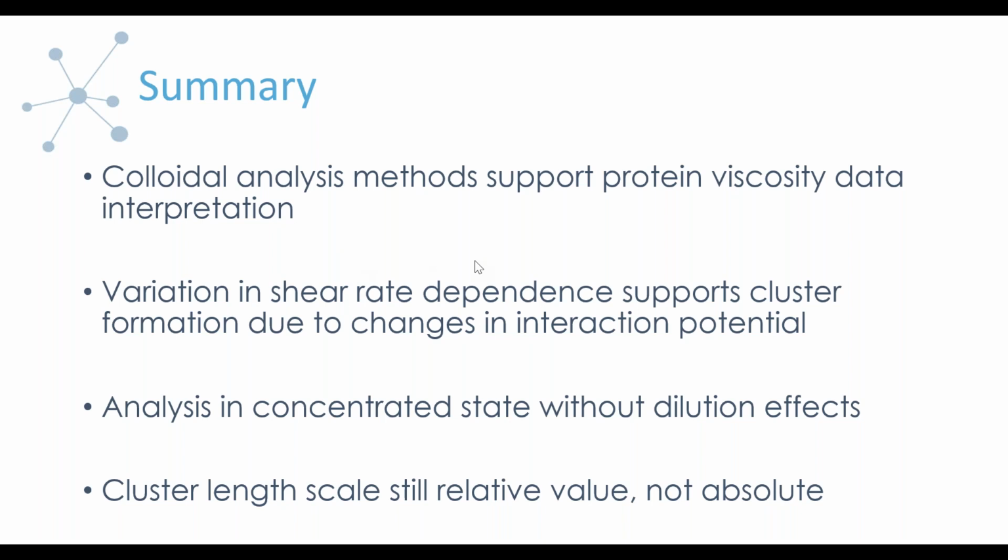Someone asked a question also about what viscosity at very high shear rate means for the colloidal framework. I didn't talk about that too much because we don't have that data, but that high shear plateau is basically the point where the shear flow has overcome all of the thermodynamic stresses in the system that are acting to keep the equilibrium state. Those would be Brownian motion, and any steric repulsion or electrostatic repulsion that exists. Basically, in that limit, all the stresses are dominated by hydrodynamics.